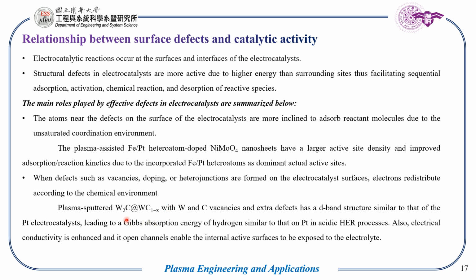for example, we can see when plasma sputtered tungsten carbide, vacancies were created in the tungsten carbide seeds, and a d band structure similar to that of the Pt electrocatalyst was obtained, leading to a Gibbs absorption energy, and this raises the hydrogen generation similar to the Pt, that is platinum, in the acidic HER process.